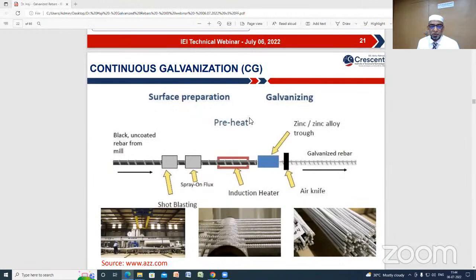Nowadays, there is a very, very new technique coming in India: continuous galvanization. The first one is batch galvanization, where you have to supply the rebar to the galvanization unit. Here, in continuous galvanization, the galvanized coating is done during the manufacturing of steel itself, and you can purchase the galvanized rebars from the steel manufacturers. Recently, one continuous galvanization unit was established in Punjab, and more units are to come in India.